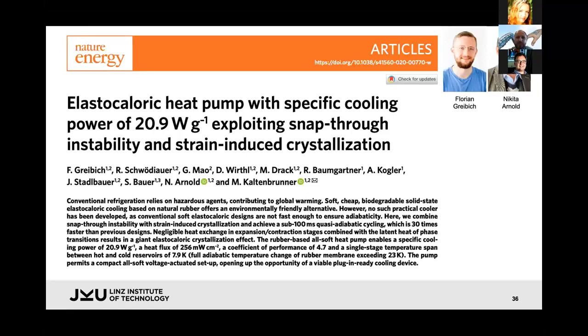So we knew that this works, and you have probably heard of the Gough effect. When you take a rubber band and you stretch it real fast, then you decrease its entropy. And by doing so, it has to get warmer because the total energy is conserved in this fast adiabatic process. And if you relax the stretched rubber band very quickly, then you actually cool it. And this adiabatic change in temperature is at the very core of every cooling algorithm. However, so far, all these machines weren't very efficient.